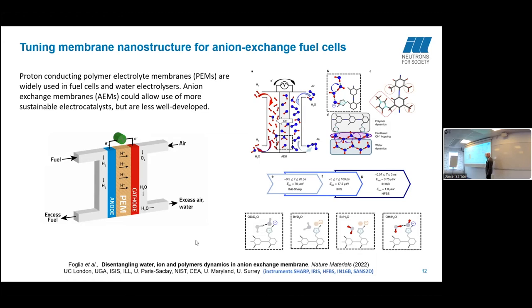So they used a technique called neutron backscattering, which involves measuring inelastic scattering from hydrogen. So by measuring inelastic scattering from hydrogen, you can determine the dynamics of molecules that have hydrogen in them. And in this case, they first of all looked at a normal sample with water, hydroxyl ions, and the polymer backbone and side group. And they were able to see the dynamics of everything, all of the hydrogen atoms in the system. So hydrogen are the methyl groups of the polymer, water, and hydroxyl. It's very complicated. Everything's piled up on top of each other.